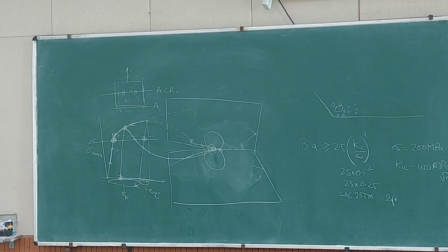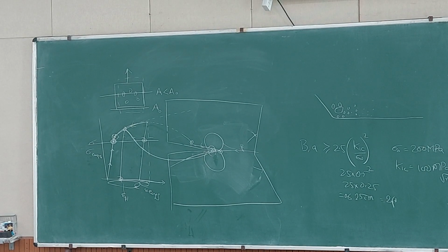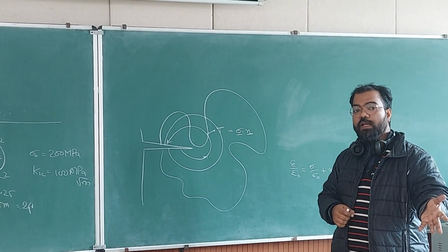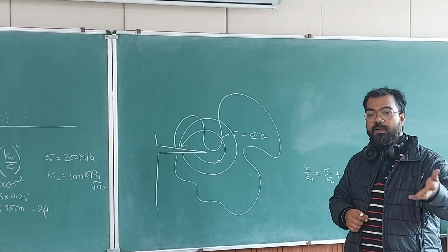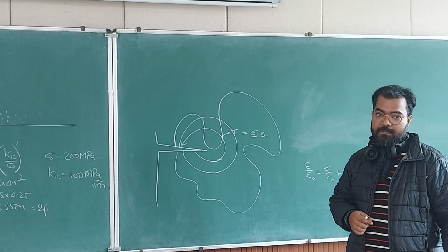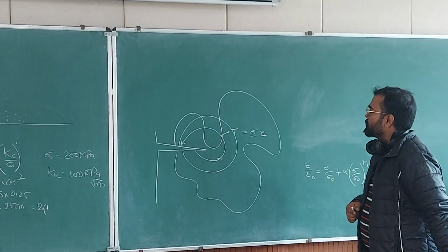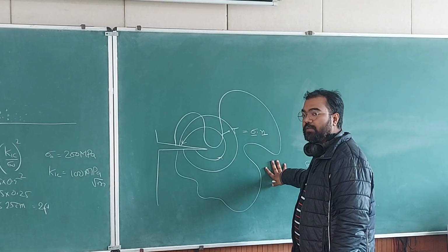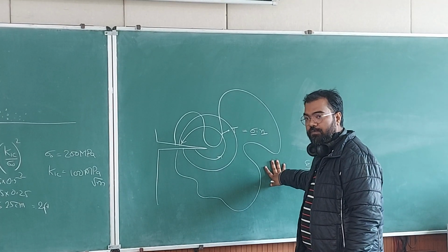So both the problems are now gone, right? So it's a non-linear elastic material and the crack is not opening up, so there is no unloading, and you have to remember these assumptions. Okay, so in that case it will act as a conservative field and I can define a line integral.